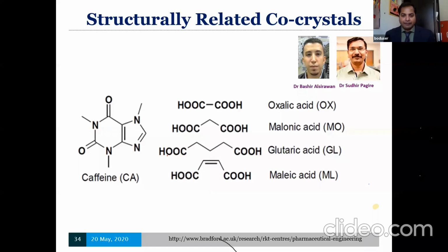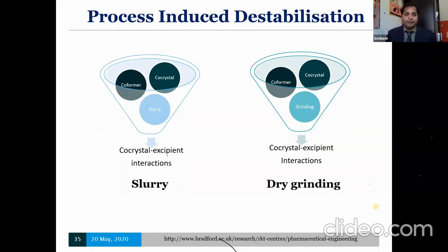if you add an additive, that could be any additive or excipient. For instance, to simplify the study, what we have taken was one of these structurally similar dicarboxylic acids. The next slide is quite simple. I think this is easy to follow. The co-crystal we have taken could be caffeine oxalic acid. A co-former could be malonic acid or glutaric acid, maleic acid, for instance, at least one of them. And we subjected them to slurry conditions and saw what happens.